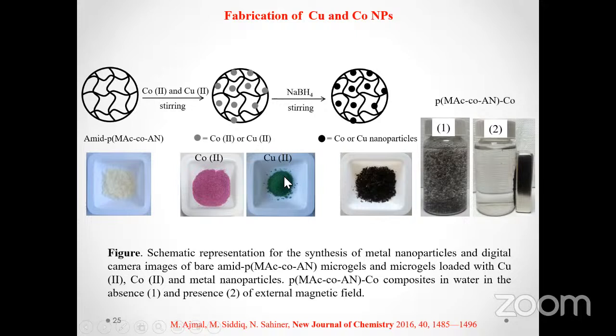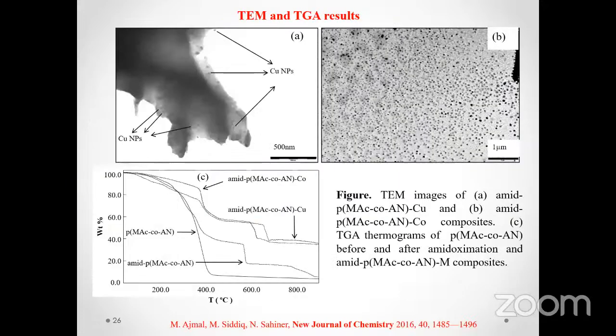And then these metal ions were reduced into metal nanoparticles, and it was also observed that the cobalt nanoparticle-containing system was inherently magnetic in nature. By applying an external magnetic field, these magnetic particles can be attracted towards that externally applied magnetic field. And in this case, we observed a very fine dispersion of the metal nanoparticles. They were well dispersed, almost homogeneous in size, almost homogeneous in shape. And this showed how effective the amido oxime groups were for the synthesis of these metal nanoparticles.